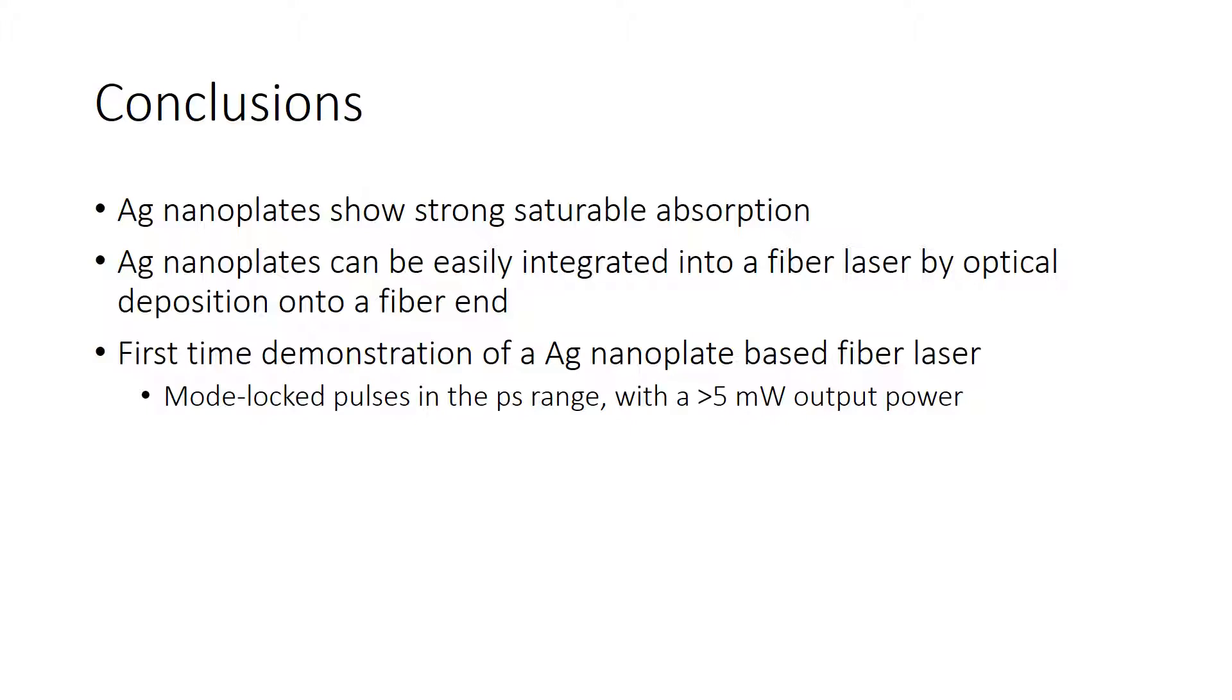And we achieved the first time demonstration of a silver nanoplate-based fiber laser that produces mode-locked pulses in the picosecond range with an output power greater than 5 milliwatts.